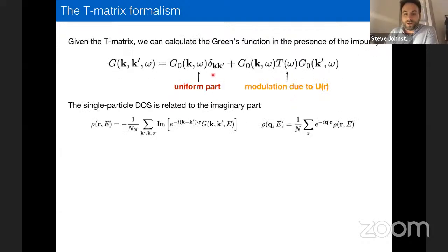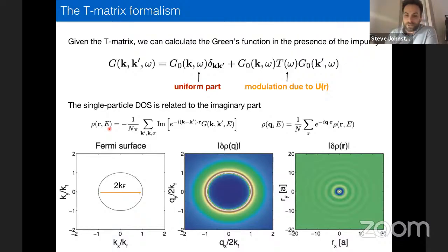Okay, and as I said before, when you insert this into the expression for the dressed Green's function, we have a uniform part. This again just corresponds to that diagram where the electron just propagates through the system. Then we have the modulations due to the impurity. Once we have this, we can then do various Fourier transforms, and we can get this either as a function of momentum and energy, or in real space and energy as well. And just to show you what these look like, if you do this for a free electron gas, this is what the results will look like if I have a nice 2kF circular Fermi surface. The Fourier transform, or the power spectrum of the density modulation, is again this nice ring, very similar to the experiment I showed you on the silver surface. And then the real space modulations look like these Friedel oscillations, similar to those cobalt or carbon monoxide oscillations I showed you at the very beginning.